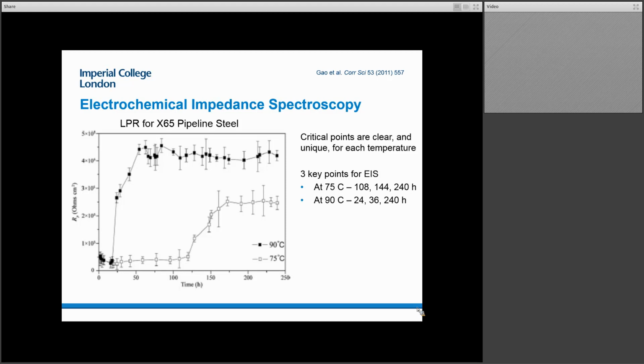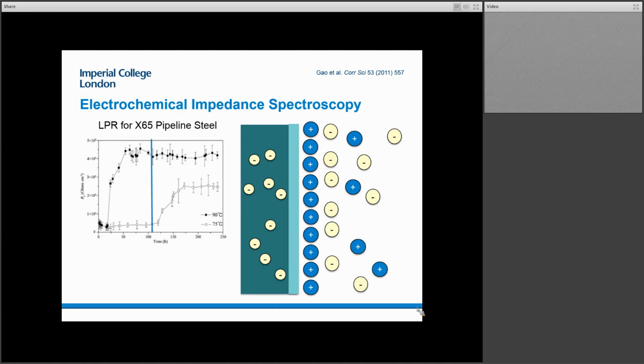So what's lovely in this experiment is they're looking at X65 steel, and they're looking at what happens when they're in sort of a seawater environment and at different temperatures. And what they see is that that resistance basically goes through three regions. It goes through an initial region where you essentially have relatively constant but relatively low resistance. Then you see a linear increase, and after which there's again another plateau at a higher resistance. And so they see this at 75 degrees and at 90 degrees, and I'm going to highlight the case at 75 degrees. So the question then is, well, what is happening in this system, right?